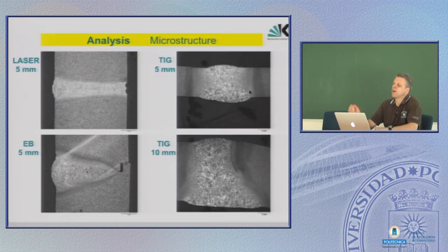And now, again, due to the transformation behavior of 9 chromium steel into martensite, depending on annealing and quenching and tempering, and due to the temperature distribution over the weld surface or volume, you produce constantly in the whole weld line base material at that point, completely hard, untempered martensite here, where all the material has been fused and cooled down rapidly, and in between it's a mix of lower annealing temperature and, at that end, higher tempering temperature.